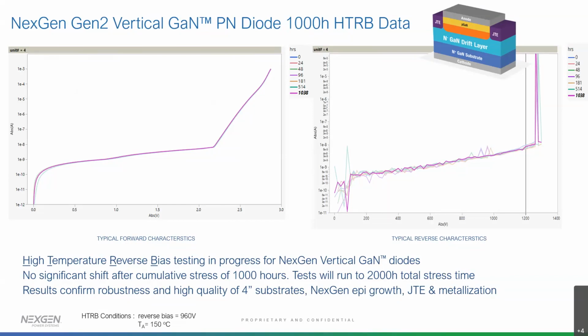So we are starting from the gallium nitride wafer. We are building the homoepitaxially grown drift layer on top of the gallium nitride wafer. We are employing the p-doped GaN region in order to create the gate or the anode for the vertical GaN diode. So it's essentially the same build-up, and by performing reliability tests, in this case high temperature reverse bias on this structure, we make sure that our major processing steps are verified and capable to deliver the reliability which we are targeting for our device portfolio.